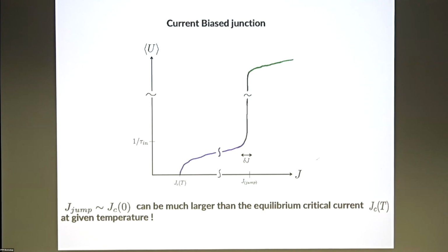It depends on time, on temperature, but anyway, there is a plateau here. This wiggle means that there is a big parameter here. So it looks like a plateau which corresponds to very small voltage and then a jump, and that's the result. But again, what are the parameters that make this region large? Theoretically, at temperature larger than the Thouless energy, the critical current is exponentially small, and this jump is not exponentially small. So theoretically, it could be even exponential, but of course, practically, it's not.